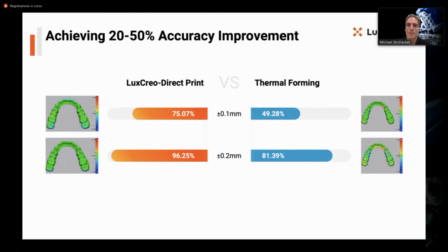So when you look at thermoforming, the scan shows 49% plus or minus 0.1 millimeters, and 81% within 0.2 millimeters. Where you look at Lux Creo direct print, it is 75% within 0.1 and 96% within 0.2. Everyone's talked about ortho only requiring 0.2, whereas restorative is 0.1 or even 0.05. These are scans, so it's looking at the surface that's within these margins and giving you a percent of the surface that's within the margin. So that's where the numbers come from.